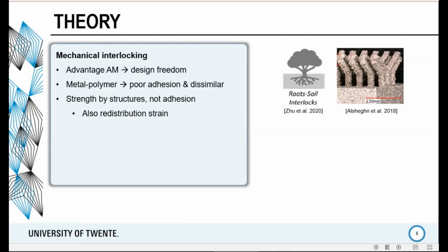And this gives you the strength of the material instead of the strength of the adhesion at the interface. So in this way, you can really engineer strong connections without being dependent on adhesion, which is useful for metal polymer connections because they have poor adhesion. And furthermore, they have really different mechanical stiffness and thermal expansion properties, which can give rise to high stresses in your material locally. And by designing this properly, you can really connect these two types of materials and you can distribute the stresses to give more stable contacts.